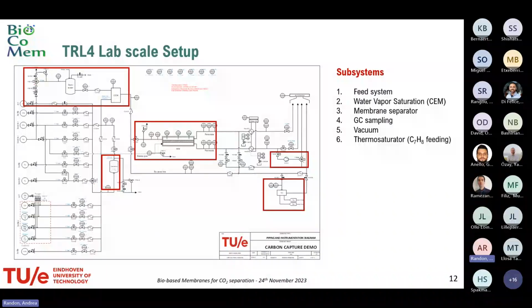Now I'm going to describe the setup that we built here at the TU/e. As you can see, on the left there is a big feed system. We can create a lot of complex mixtures to test our membranes. And there are also the pollutants that we need for doing the aging test. Once the mixture is created, it is conveyed through the water vapor saturation unit, the controlled evaporation mixing unit, the CEM. For the CEM, we need to supply the gas mixtures and also the water coming from a demi-water tank, which is pressurized through nitrogen. There's a flow controller. I calculated all the molar fractions that I need to saturate the different components.